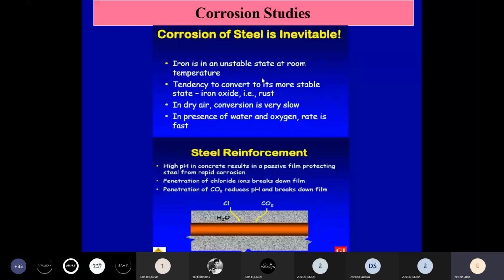Carbonation induced corrosion generally happens in areas where the humidity is about 50 to 75. And it basically happens in the parts of India which are semi-arid or dry regions, like Delhi, Rajasthan, Jaipur, Madhya Pradesh, etc. The dry regions of the country are more susceptible to carbonation-induced corrosion. But chloride-induced corrosion happens near the seabed. Talk about Bhavnagar, the structures which are in coastal regions. Talk about Diu, Surat, Bombay, Chennai, all those structures which are on the coastal belt, they are prone to chloride-induced corrosion. So let's talk about the first mechanism, carbonation.